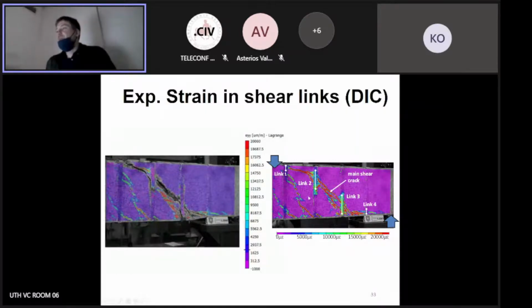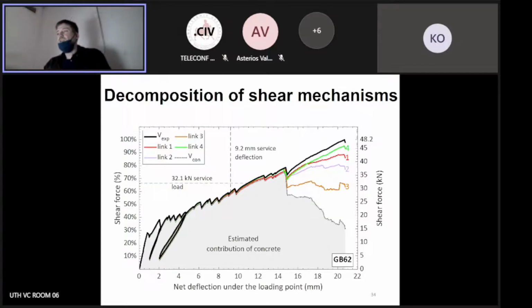links we achieved. What I did later is I took all the beams and I calculated the utilization of these links only based on the active bond length, the length that was really activated. This is really the most accurate way to estimate how much job those shear links did. And then I calculated the shear force produced in every one of the links and subtracted it from the total. So at the end, I had the contribution of the shear reinforcement, which was basically this, and everything else was the contribution of the concrete. This point is the shear cracking. So this is where the shear crack starts, and this is what we got as a contribution of concrete.